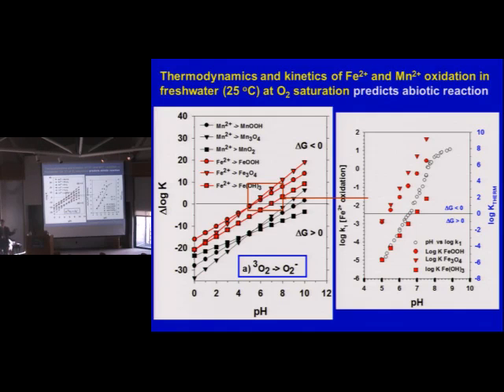And as it turns out, these are pi electrons coming out of the iron 2 going to oxygen. And that's the perfect one for Marcus theory. If you had manganese 2, it would be coming from a sigma orbital going to a pi in the oxygen. That is an unfavorable process, all right, because there's an orbital mismatch. So what you see here is the thermodynamics telling you why the iron 2 would be in banded iron formation.